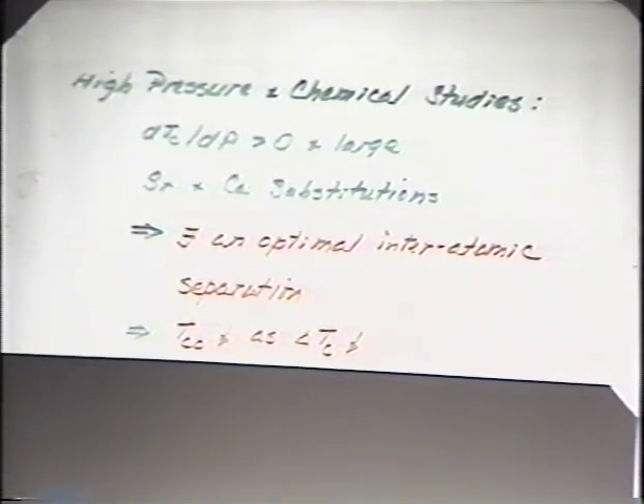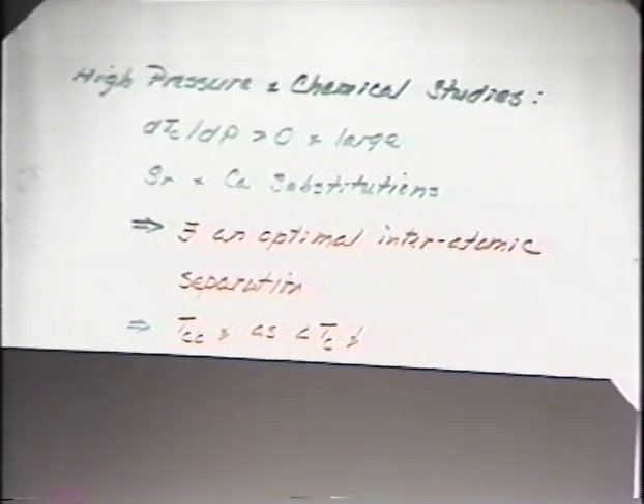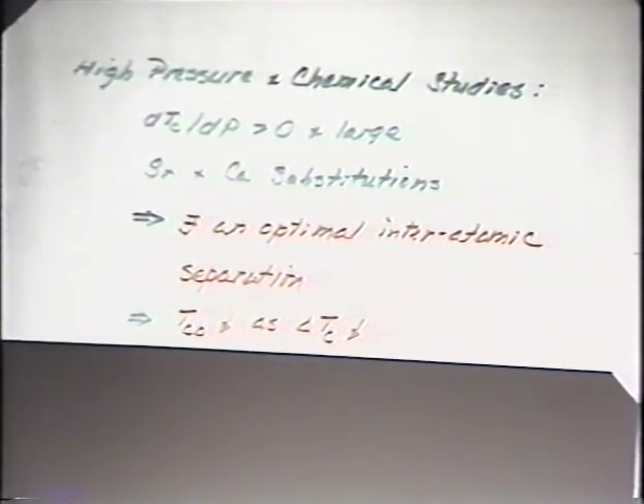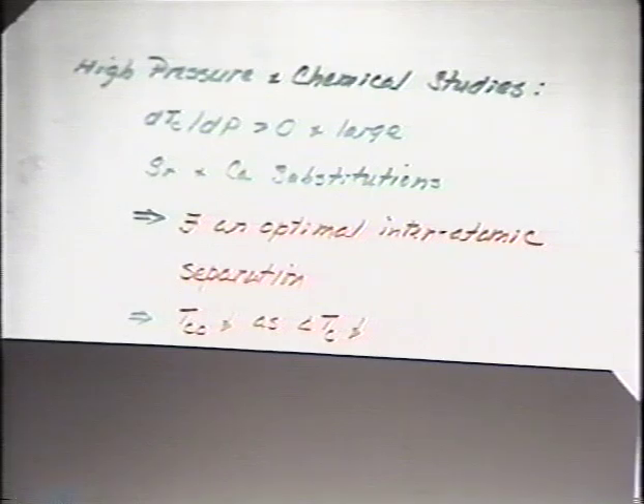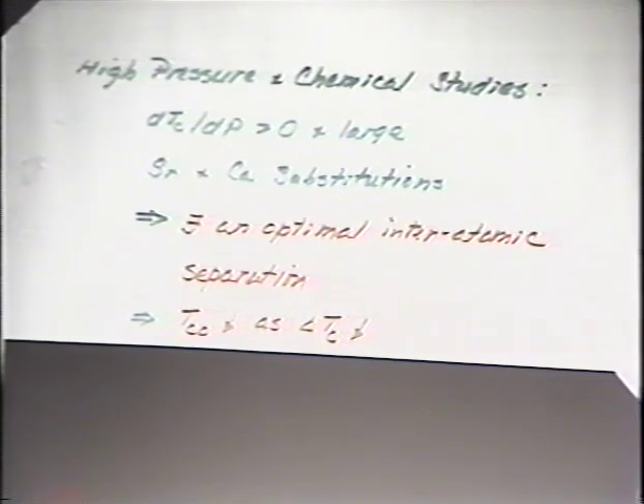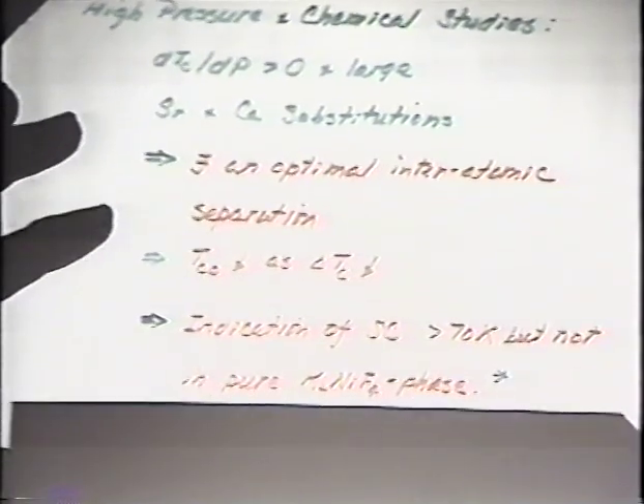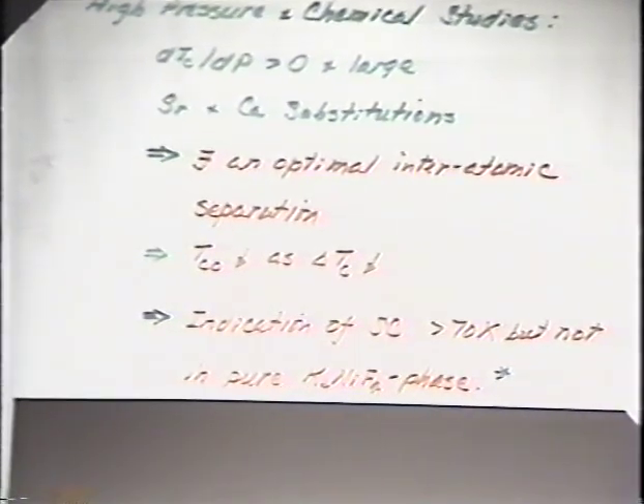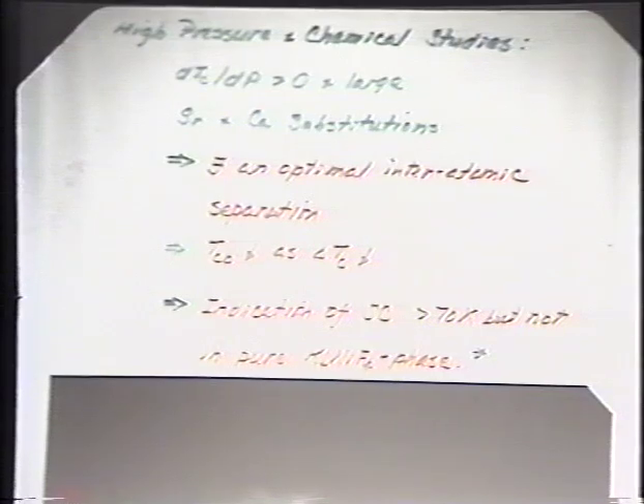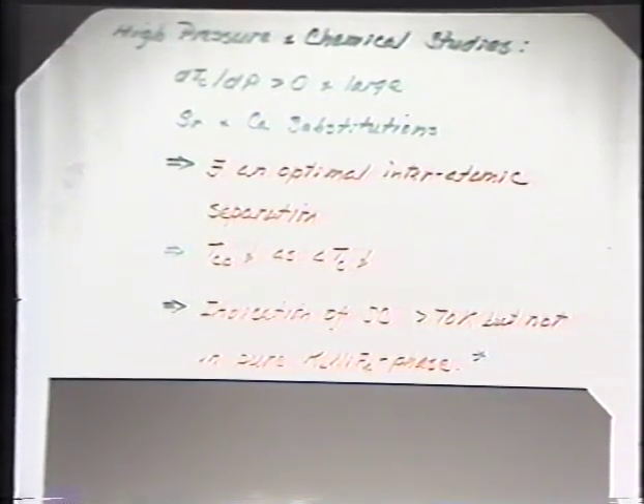We found out that the TC, the onset TC, usually goes down when you make the material purer in the so-called layer structure, and also when the width of the transition goes down. So this tells us something. And by that time, we had observed lots of indication of superconductivity at temperatures higher than 70 Kelvin, but only in those materials without the layer structure as the main phase.